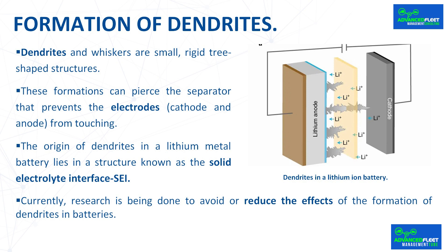Researchers at the Next Generation Battery Research Center at the Korea Electrotechnology Research Institute developed a porous carbon structure with a hollow core and a small number of gold nanoparticles with an affinity for lithium within the core, to be used in lithium metal batteries and avoid the formation of dendrites. In the new structure, gold controls the growth direction of lithium by reacting with it, inducing lithium deposition inside the core. The results showed that reducing the diffusion length of lithium ion through the pores of the shell and improving the affinity of lithium for gold nanoparticles maintained lithium deposition within the structure, even under high current loading conditions.